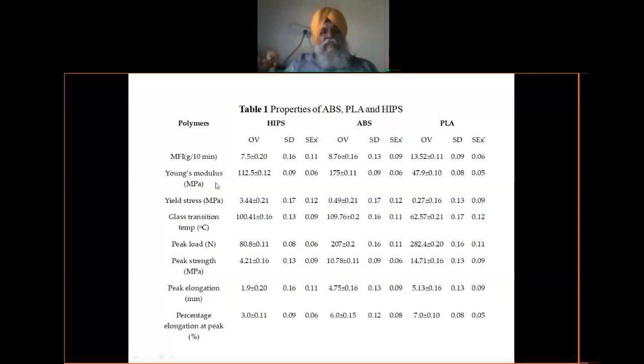Then there is a change in the Young's modulus of the material. PLA was having a minimum Young's modulus. Similarly, there is a change in the yield stress. There is a change in the glass transition. You can see for HIPS, the glass transition was 100. For ABS, it was 109, and for PLA, it was 62. Then similarly, properties like peak load, peak strength, peak elongation, and percentage elongation were also observed. Then we tried to see the multi-material printing at some fixed parameters.